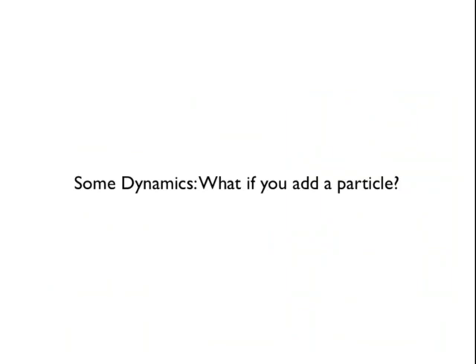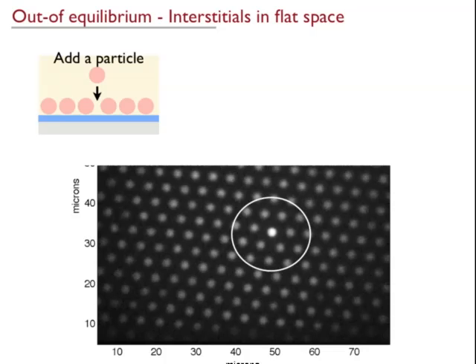Okay, so far we've kept the number of particles fixed. Now what we're going to do in the last couple of slides, before I get thrown out, is show you what happens when you add a particle. Typically, when you add a particle to a crystal, it's supposed to go in as an interstitial, between the lattice sites. An interstitial is supposed to be completely innocuous. It has no topological charge, no Burgers vector, nothing. If you strain the crystal, you shouldn't even move it. All it's supposed to do is diffuse around.